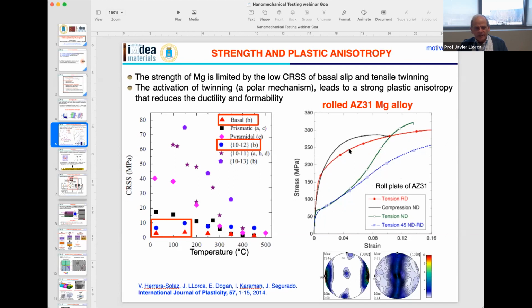Then what you have is pyramidal slip. The critical resolved shear stress for pyramidal slip is very large, so you have a very large flow stress. On the contrary, if you deform this material in tension along the normal direction or at 45 degrees between the normal direction and the rolling direction, you are able to activate twinning. And because the critical resolved shear stress for twinning is much smaller, you have a very low value of the yield strength of the material. So you have a material with a very strong plastic anisotropy. And this very strong plastic anisotropy is very detrimental from the viewpoint of ductility and deformability. So this is something you just want to avoid.